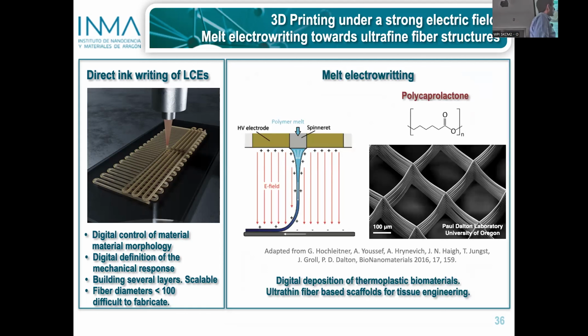So we decided to explore this technique, that is melt electrowriting. Melt electrowriting is a technique developed by Paul Dalton, released in 2011, and essentially the principle is very similar to that of extrusion, but in this case, a high voltage is applied between the nozzle and the collector, the receiving substrate. So a strong electric field is generated in this area. The polymer gets charged, and the fiber is drawn. Even with very little pressure, the fiber can be drawn to the substrate, as we will see in the next slide. And this generates very thin, ultrathin fibers that can be precisely positioned,